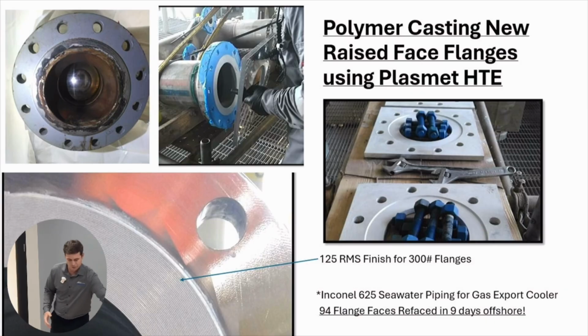You paint this with a bond release agent. You blast the surface of the flange. I mean, these flanges were eaten up. They were losing seals. It was a major problem. Fill in the pits, prime it, bolt this to the surface, like you can see my colleague here. You torque it down, leave it in place for 4 to 6 hours, pull it off, finish it, and you're done. We did 94 flanges in 9 working days.